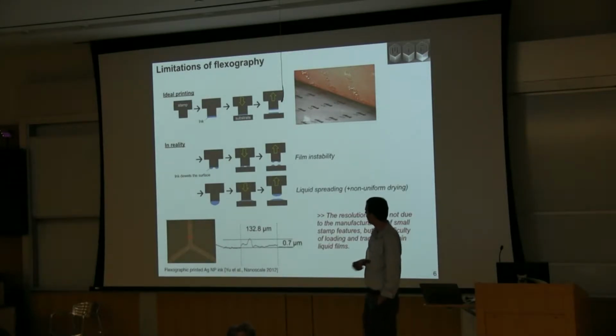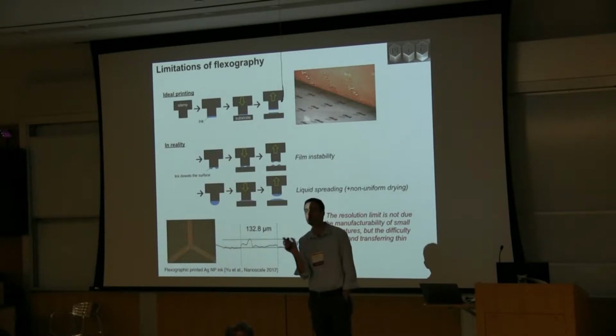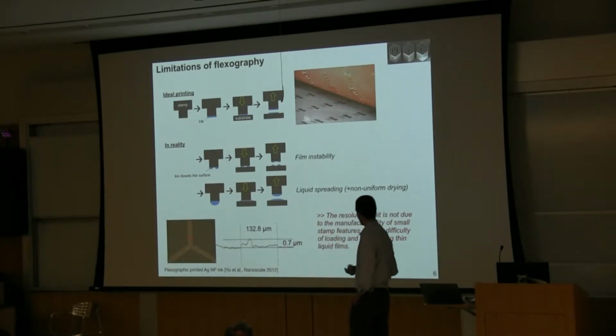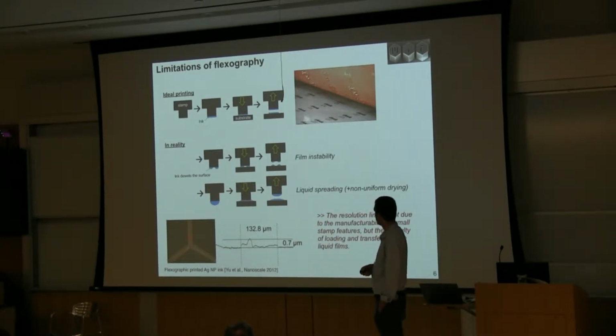But what happens in reality when you do flexography is you're limited to printing features of about a few tens of microns wide by fluid mechanics. And you can have two basic problems. One, you can have instability in the liquid film on the stamp. If you make your film too thin to make this thin printed layer, then the ink will de-wet the stamp surface and you have a broken feature.